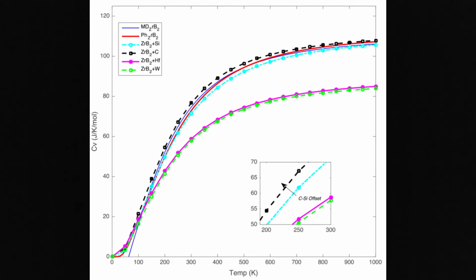When the lattice vibration reaches its maximum, the phonon contribution will not increase even with temperature, based on the Debye model. Phonopy applies the quasi-harmonic approximation, QHA, which is not applicable at very high temperatures of complete anharmonicity. Hence, in this study, specific heat capacity in the temperature range of 0 to 1000 Kelvin has been investigated.